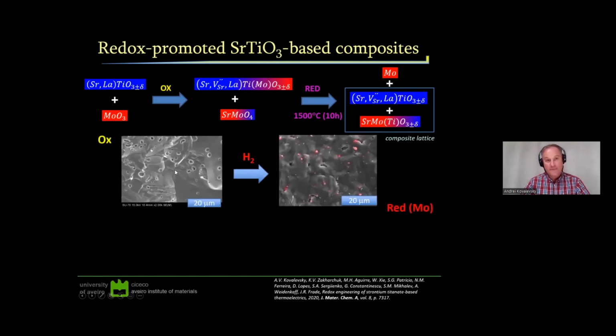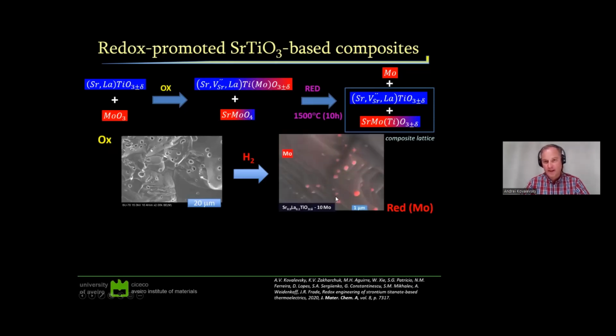Initially we have the molybdenum dissolved in the lattice in different forms. Then after application of reducing conditions, we get the formation of this nice composite structure, with particles of molybdenum that can have quite small size, which is very promising for suppressing thermal conductivity due to phonon scattering effects.